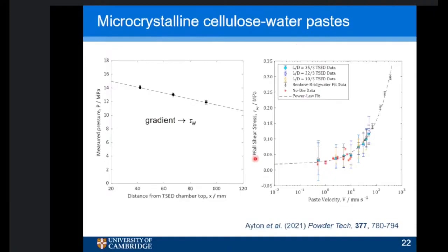And what you can see here is plots of wall shear stress against the plate velocity, against different ways of measuring it. You can see we've got error bars, so there's some variation. What can you see here? You can see that this wall shear stress is strongly related to the velocity. So it goes up quite a lot with the velocity in a parallel way. But in terms of the different lengths of the die, because that's what the 35/3, 22/3, and 10/3 mean, you can see that this wall shear stress is not really related to the length of that secondary die, which means it's not pressure dependent. So for this pharmaceutical material, we don't have to worry about pressure effects. For the tungsten carbide ones, you can work out for yourself why they don't want me to show you the results. Anyway, let's move on to something else.